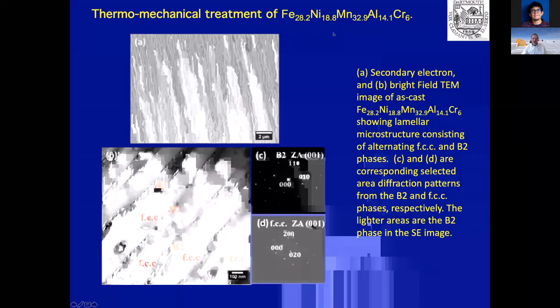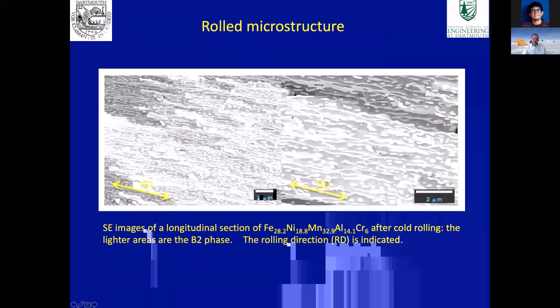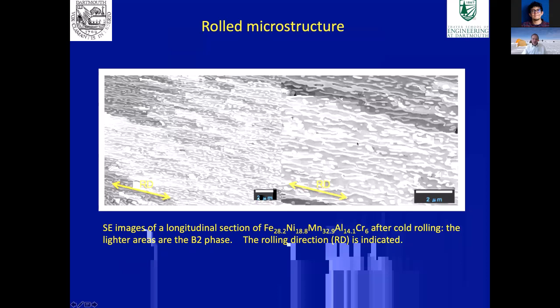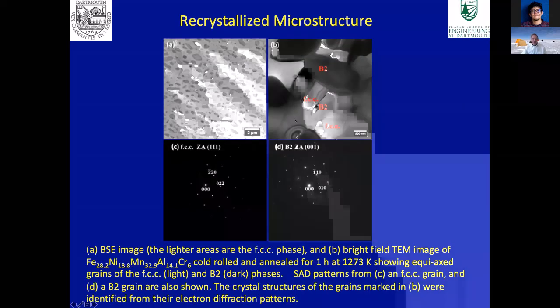So one of the things we've done is a thermomechanical treatment of this alloy as well. So this is the initial microstructure, and this is an alloy which we've added chromium to. And we cold roll it, and this is what it looks like after cold rolling. So we've got an alignment of the lamellar structure, and then we anneal it, so we recrystallize it. And after recrystallization, we now get this sort of microstructure. And what this consists of is actually equiaxed grains of a B2 phase and an FCC phase.